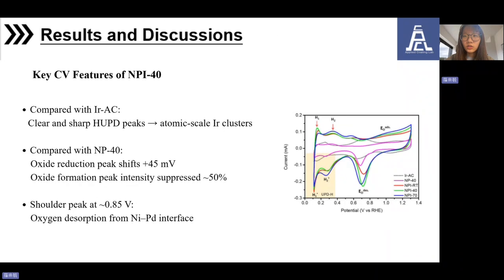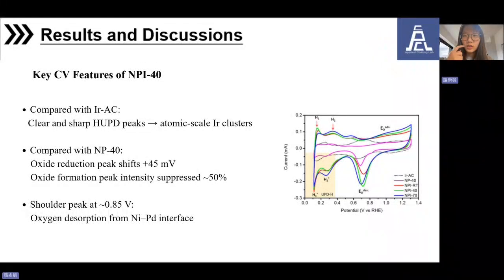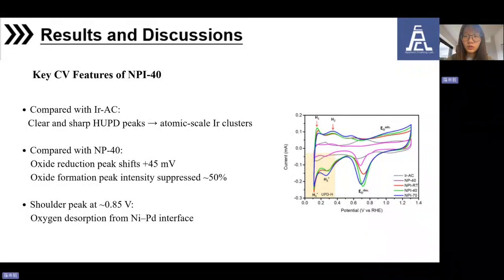In addition, a shoulder peak appears around 0.85 volts, which is attributed to oxygen desorption occurring at the nickel palladium interface. Overall, the CV results suggest that NPI-40 provides the most favorable surface chemistry for the oxygen reduction reaction.